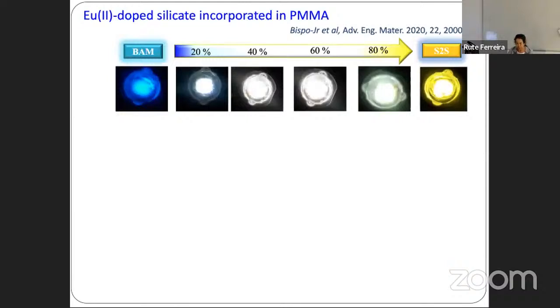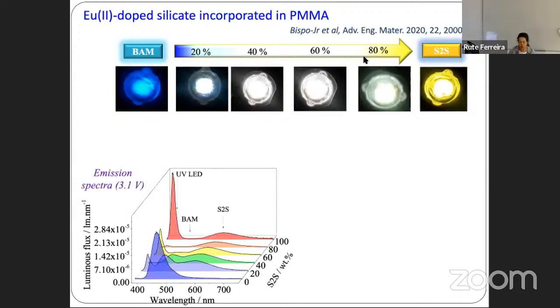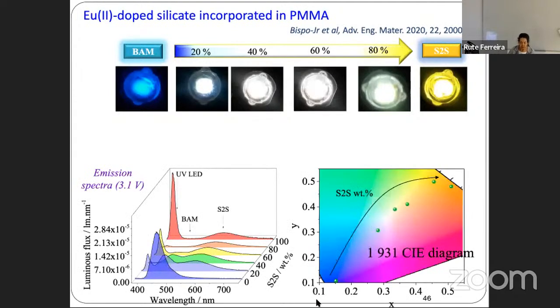By varying the ratio between them, between 20 and 80%, it is possible to tune the emission properties. Here you can see that we can tune the emission from the blue to the yellow spectral range, crossing the very important white region that is the center of the diagram. If you look in greater detail at the emission spectrum of those prototypes, you can clearly identify that the relative contribution of the commercial oxide can be tuned, and therefore we can control the properties.